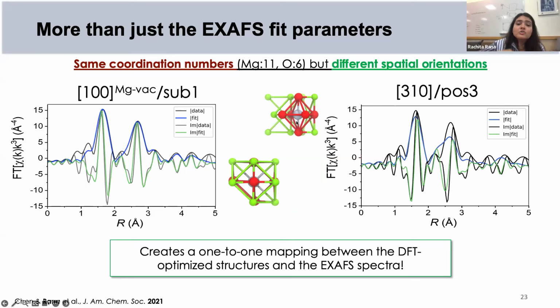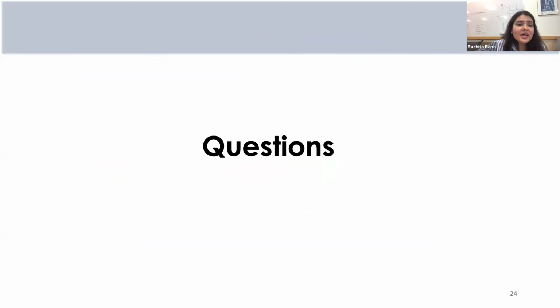And because we are doing this one-to-one mapping of the experimental data with the data from the DFT database, we're able to get the spatial orientation of those atoms that are neighboring our central atom. And that's how we're able to capture anisotropic effects in our material. That's really important when you're talking about these dispersed atoms that are catalytically active. So with that, I'll take another break and I'm happy to take questions.